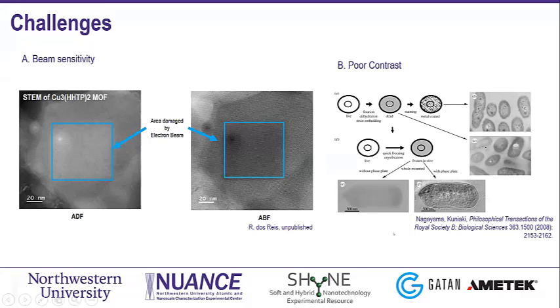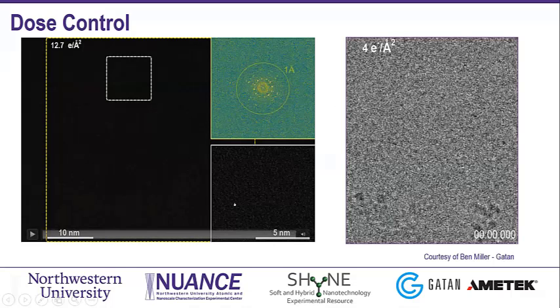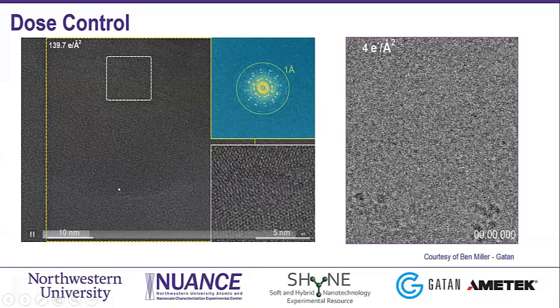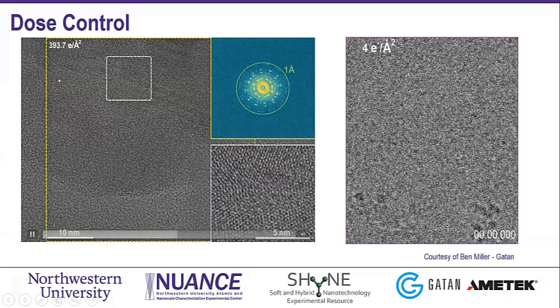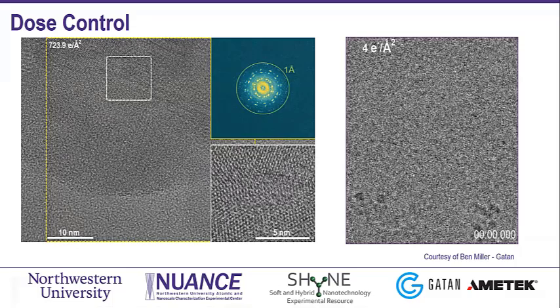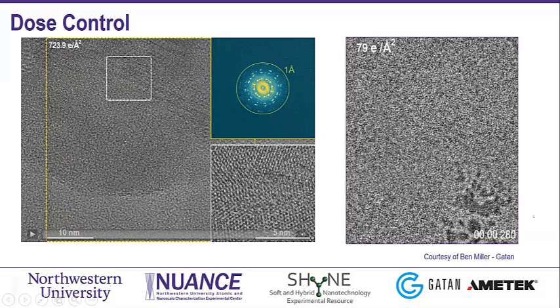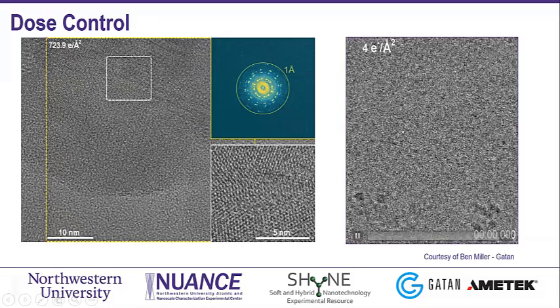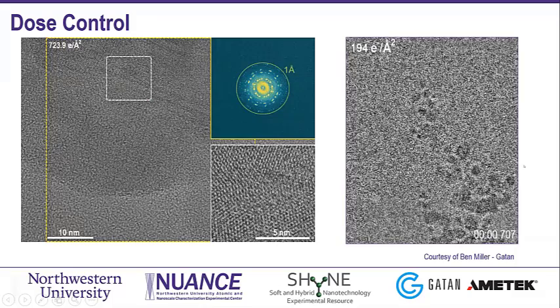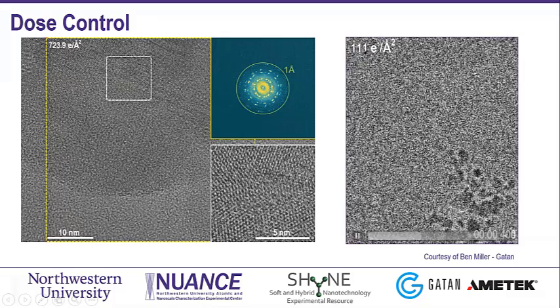So how are you going to come across those two challenging points here, right? So first thing is take advantage of the direct detector cameras to control your dose. So this is a nice example, nice videos done by Benjamin Miller from Gatan using our K3 IS here at Northwestern. So you can really control the dose while you acquire your data. And then I'm going to show you later on the live demo as well. And really, this is a TEM mode just for reference. And you can really follow the morphology variation while you control the dose, right?